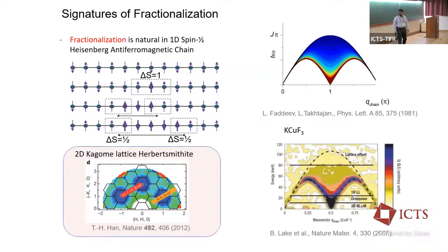And of course, that has been shown to be the case in many systems by now. For example, in an antiferromagnetic spin chain, where you have spinon deconfinement, you get this broad scattering continuum, which is sandwiched between two envelopes, one coming from the ferromagnet, the other coming from the antiferromagnet. And also in the kagome lattice quantum spin liquids in Herbertsmithite.